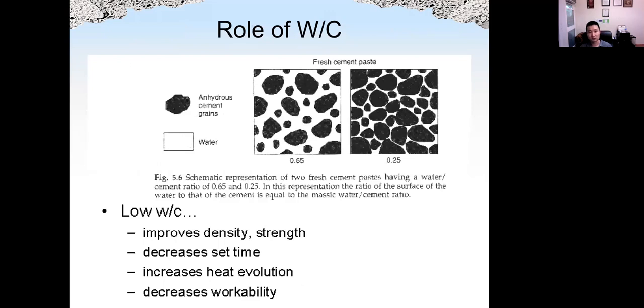The role of water-cement ratio. The water-cement ratio is the number one factor controlling the strength of concrete. Higher water-cement ratio, lower strength. Lower water-cement ratio, we have higher density and higher strength, but the setting time will also be shorter. So keep that in mind. And we also have higher temperature due to higher heat evolution, and the workability will of course be lower. That's why for high strength concrete, we need to put a superplasticizer in the system.